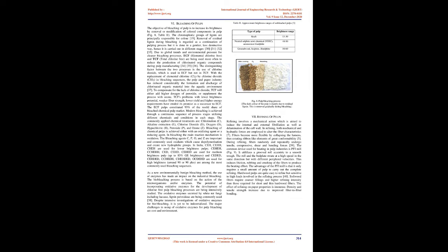the initial, bulk, and residual delignification phases. 25. The initial phase or impregnation stage is controlled by diffusion, which is affected only by the total cross-sectional area of accessible pores. 26. In this phase the selectivity is low and only 20% of total lignin, mainly low molecular weight lignin from the middle lamella, is removed.